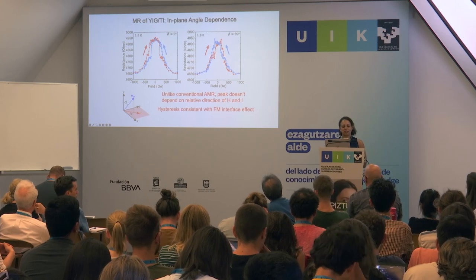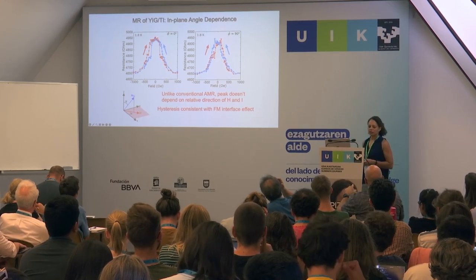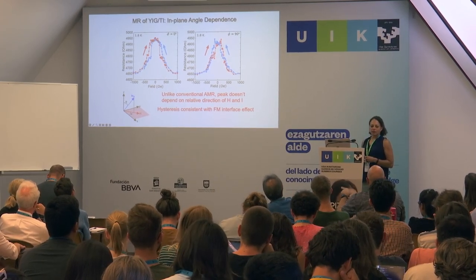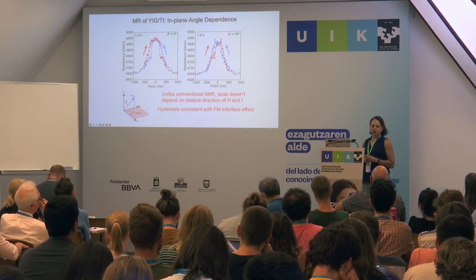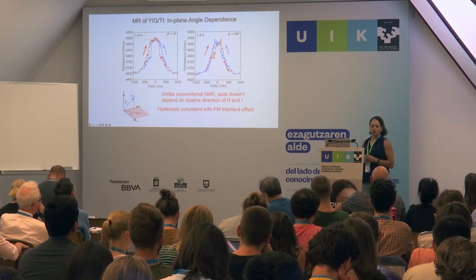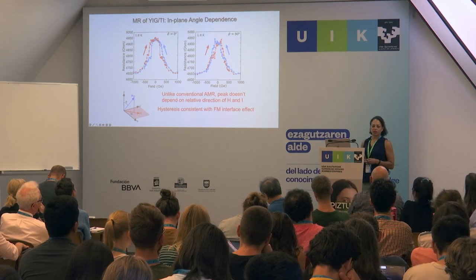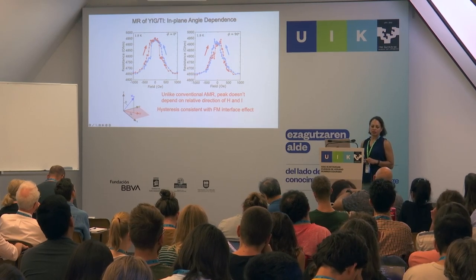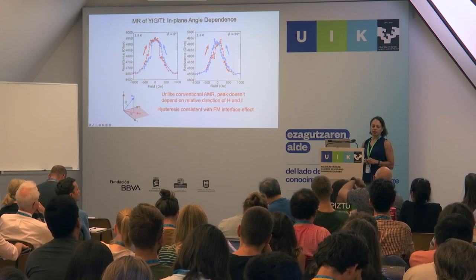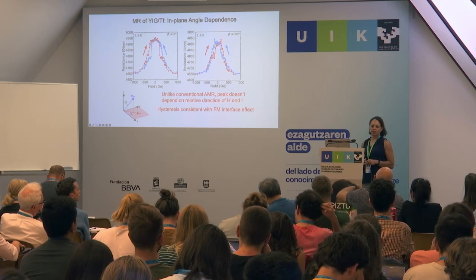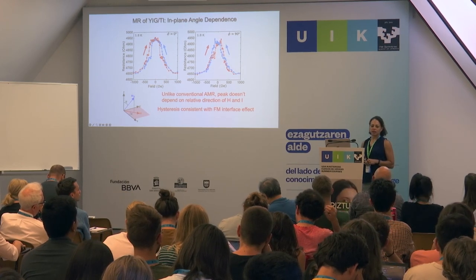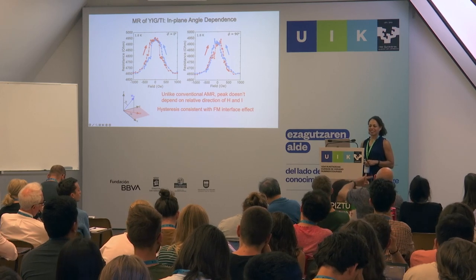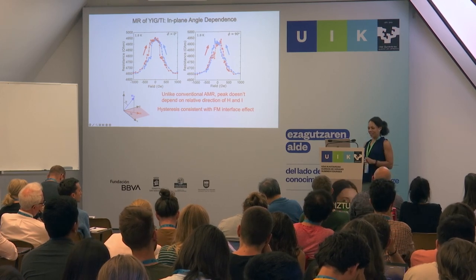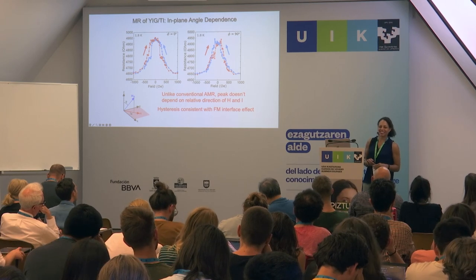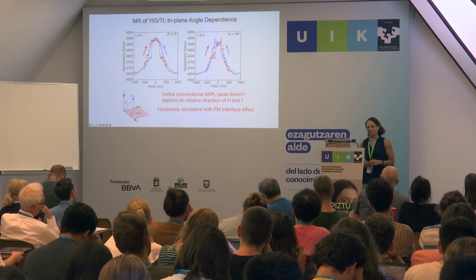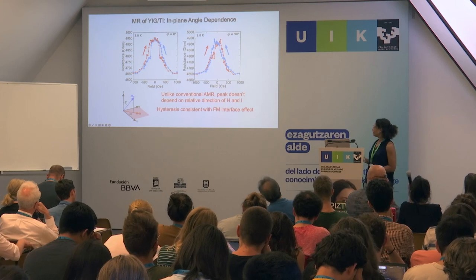So that hysteretic curve for the YIG parts, was it measured with the topological insulator attached, or just YIG without? Just YIG without. But then when you put something on top with spin orbit coupling, you can just get anisotropy from that, right? Then it's sort of reasonable that the field is much larger. If it's an easy axis anisotropy, yes. Then of course it'll be much larger than the switching field. Yes, which is what we see. That's exactly right. That's exactly what we see.